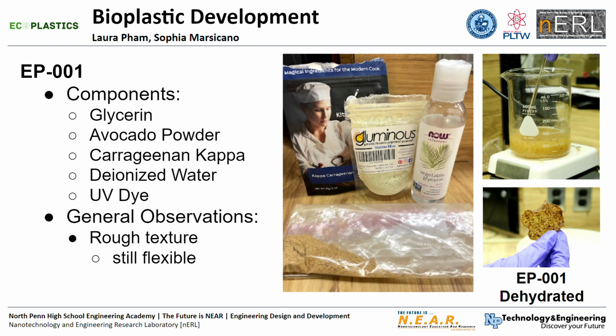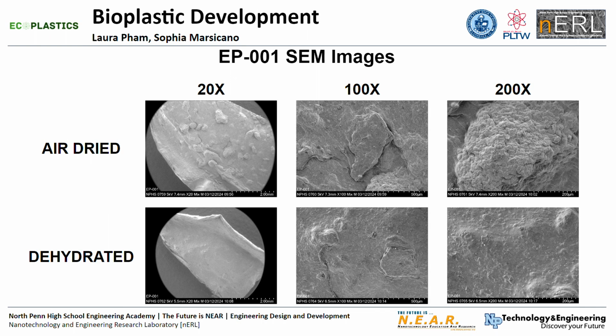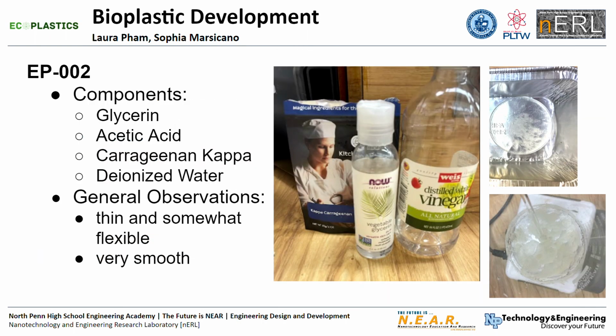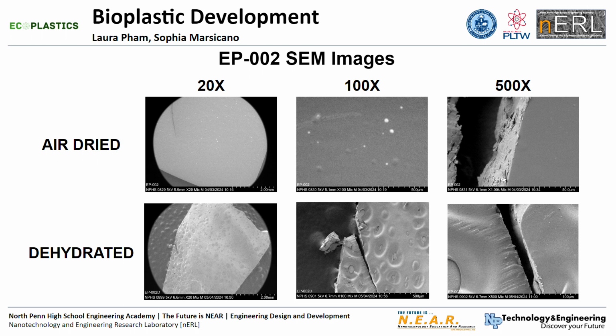In outward appearance, EPO1 had a rough texture due to the avocado, yet it was still flexible. And that rough texture I just mentioned is especially evident in these SEM images. For a second bioplastic, EPO2, it consisted of carrageenan kappa, acetic acid, which is commonly known as vinegar, glycerin, and deionized water. This plastic ended up looking a lot like a typical plastic you'd see. However, it was very brittle compared to EPO1. Now, seen in the SEM images, there's not much texturally to EPO2 besides the occasional air bubbles.